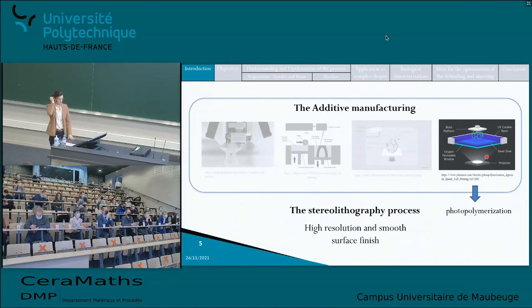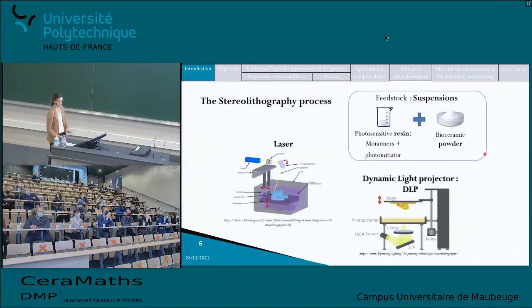So the stereolithography process uses suspensions as a feedstock. A suspension is made of the photosensitive resin, which is composed of different monomers and the photoinitiator, which is at the center of the photopolymerization, mixed with the bioceramic powder, which is the powder that we want to print. There are 2 different types of stereolithography process: the ones using lasers as the light source and the ones using a dynamic light projector as the light source, these ones enabling to cure the whole layer at once.